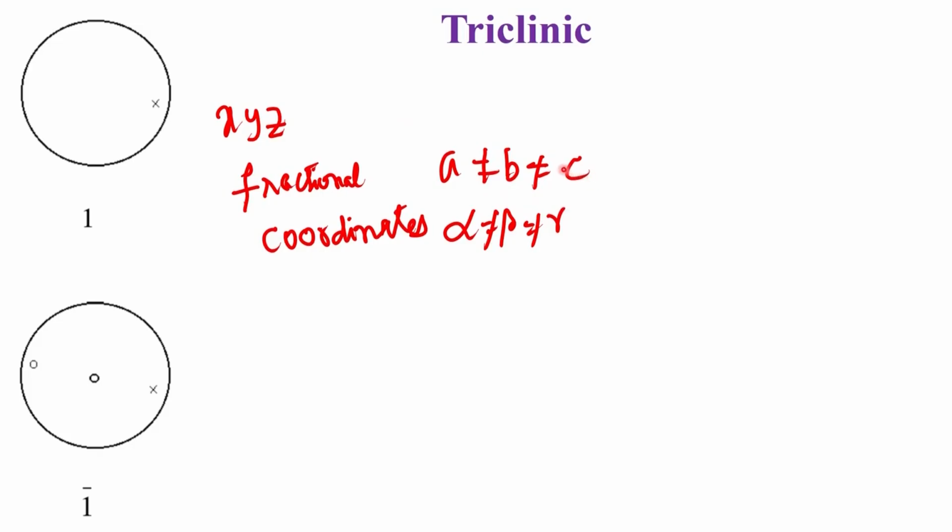This is a very important point, because when we talk about the coordinate system in a triclinic system, we should not assume that the x, y and z are coming from a rectangular coordinate system. That means the 90-degree angle is not there in this system. So, people who do energy calculations and theory calculations based on this kind of information should convert the x, y, z to the proper set of coordinates before they use their theoretical approaches, because most of the theoretical approaches assume the system to have 90-degree angles, and A, B and C will then correspond to x, y and z axes.